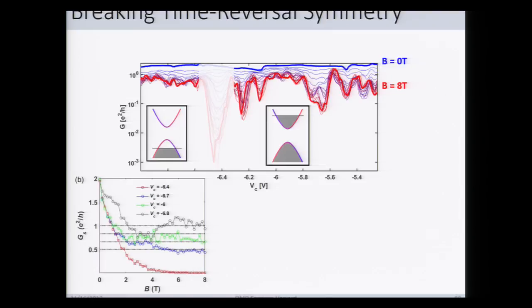And just to give you an idea, at a few selected gate voltages, here's the conductance as a function of magnetic field. And you see it drops initially and then starts to saturate at high magnetic fields. Here in red is the data at this gate voltage where you see it's really trending towards 0.